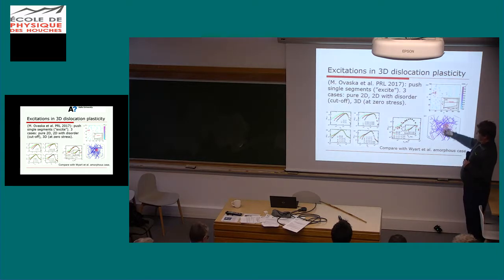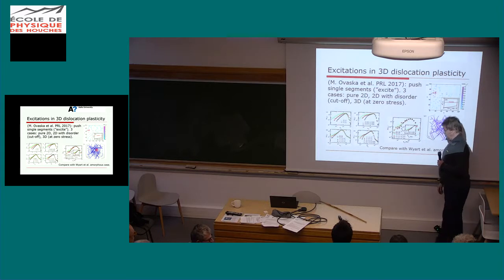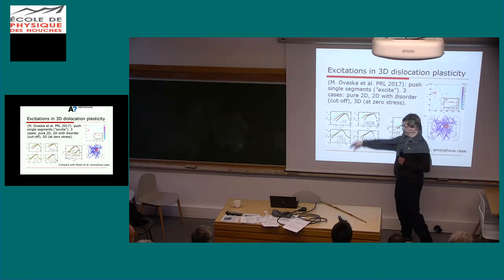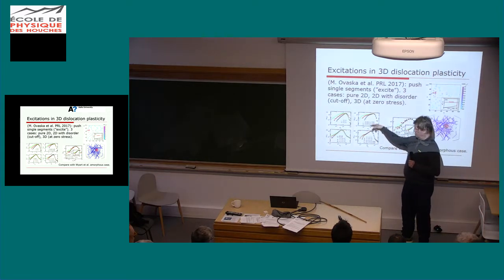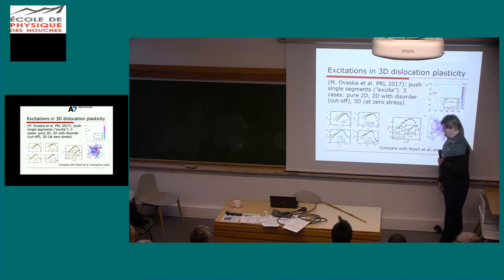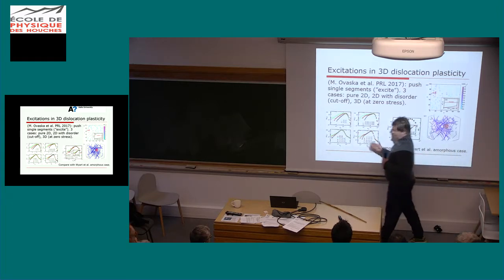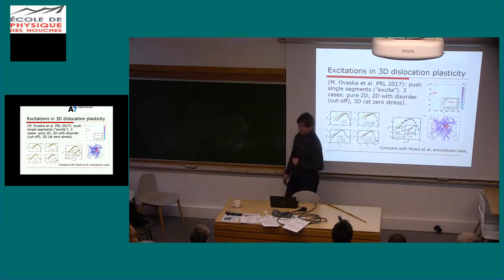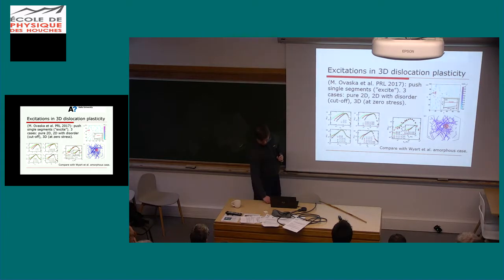You can take a 2D or 3D system, you can apply an increasing local stress to one of these topological excitations, be it a segment in a 3D system or one of these particles, and you can see at which stress this actually incites an avalanche, so then you get the excitation spectra. An important point here is again that these are scale-free, except if you have disorder, then you get a cutoff. The 3-dimensional data is really rough, forgive my language, but it still looks pretty much as you would expect: there are extremely soft modes in the system that you can excite.